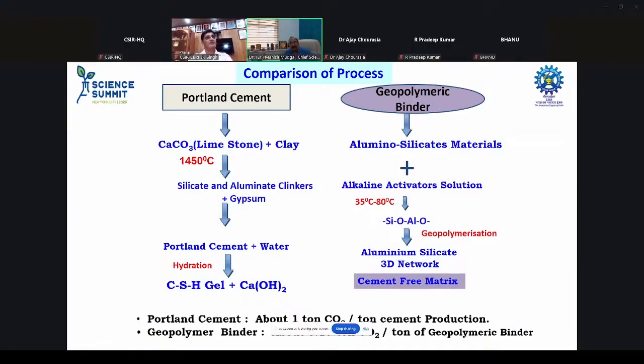When we compare Portland cement with the geopolymer, the Portland cement process is highly energy intensive, and in the geopolymeric process we need only 35 to 80 degrees centigrade. Another advantage of geopolymer is that it doesn't require water curing. And it is 83% less carbon dioxide emitting concrete. Only 0.17 tons of carbon dioxide is emitted per ton of geopolymeric binder. So both the geopolymer binder and concrete are eco-friendly.